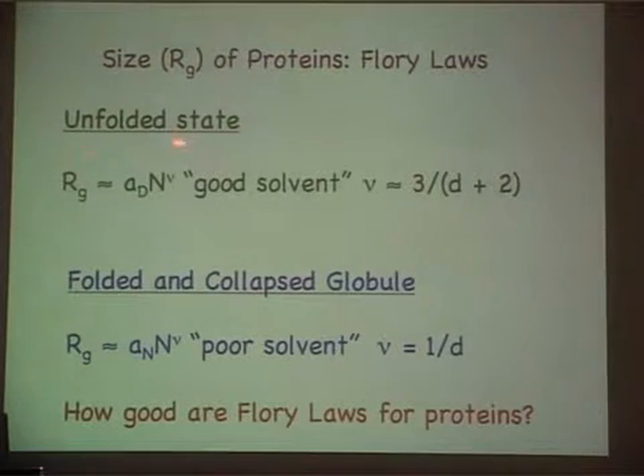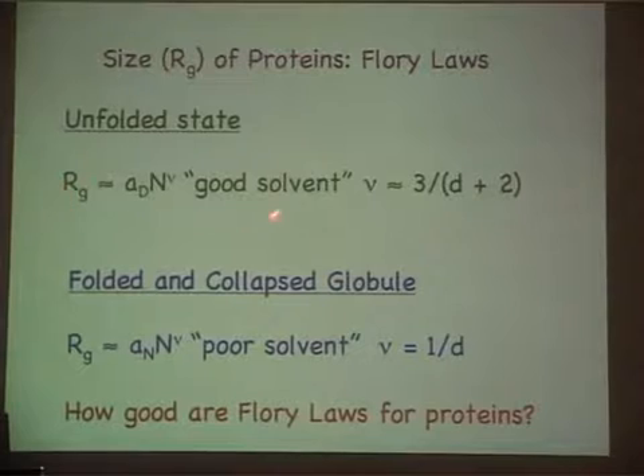So if the unfolded state that you created by adding, say, denaturants is indeed a good solvent, in the sense Flory told us, then you expect the Flory laws to be valid. The radius of gyration must scale as the number of amino acid residues to the power nu times a prefactor. And nu is given by 3 over d plus 2, so in 3 dimensions it's 0.6, roughly speaking. So this is one of the important things that you should remember if you want to estimate the dimensions of a polypeptide chain.